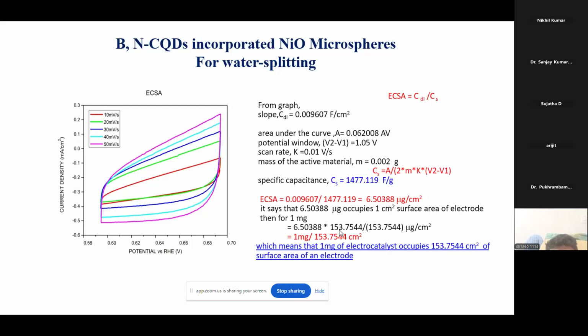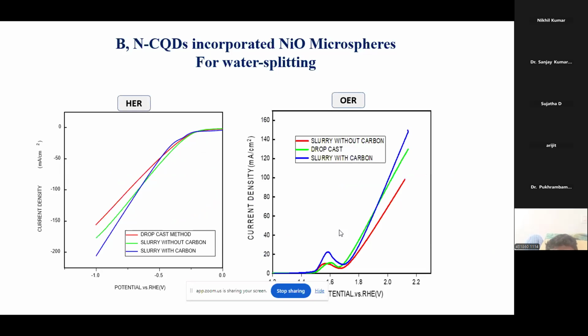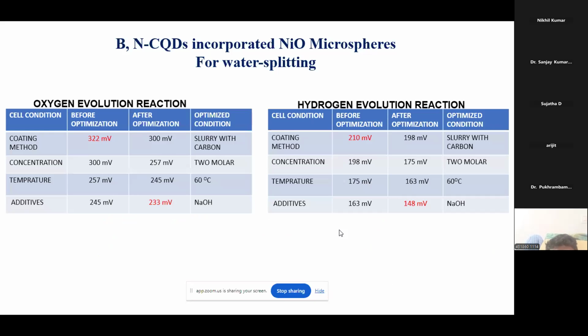Then there are different types of methods we use to cast it, like on nickel foam, how we cast it and how the performance varies. For the oxygen evolution reaction OER and HER results that we optimized, we changed parameters like the coating method, the concentration level, the temperature and additives. Due to NaOH, it has a corrosive nature, but it also enhances the result output. So we used this one and optimized.